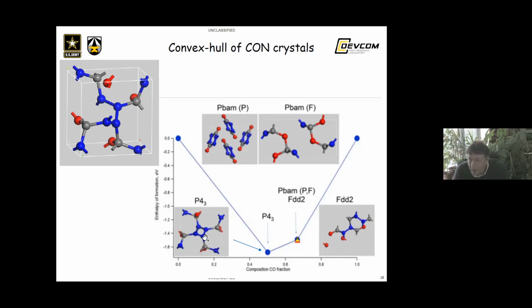But this is our structure. And from the top view, this thing looks like a square. It is not a square. So I rotated this a little bit. And this structure in the middle is a spiral. This structure was also obtained by a Chinese group. And they predicted that it might be stable at ambient condition. Unfortunately, experiments by Chun Shi Qiu showed that it's not true. This structure is decomposing at 20 GPa to epsilon phase and at 10 GPa to delta phase. So it's not recoverable.